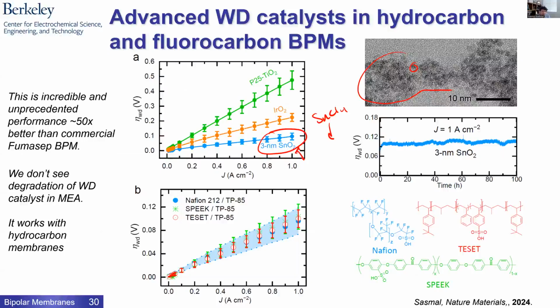So if I had put the commercial bipolar membrane on here, the polarization curve would be sort of like this. It would drop quite a bit of voltage, maybe 400 millivolts at 100 milliamps of current. The best ones are now more about 50 millivolts of driving force at an amp of current. So this is functionally transparent. This can be put in any device and you basically don't lose any free energy. You can do it with lots of different polymers. It really works. And tin oxide is a very stable compound. There's no reason for it to degrade.